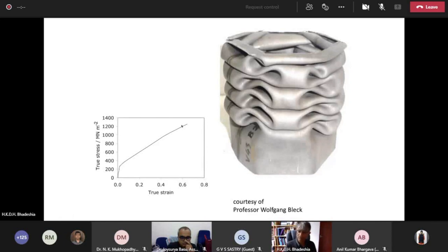So it turns out that it's not actually suitable for this crash-resistant application simply because it starts off quite weak and then reaches a strength of 1.2 gigapascals. And the way in which this component is designed means that you do not get uniform deformation. So much of this remains at a low strain. So do you abandon this idea?